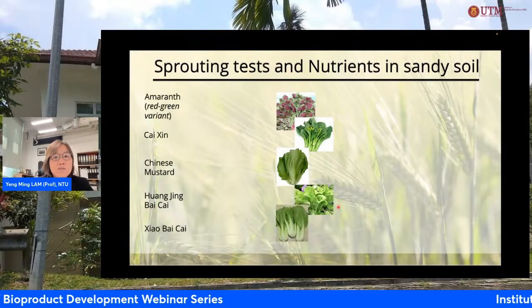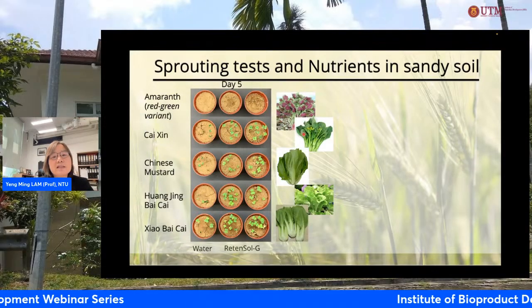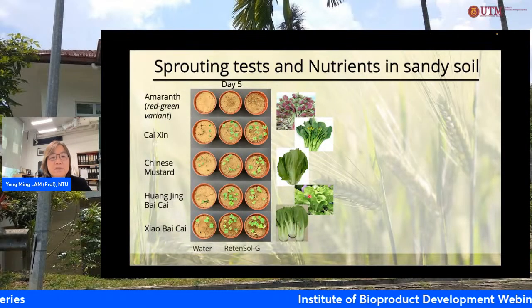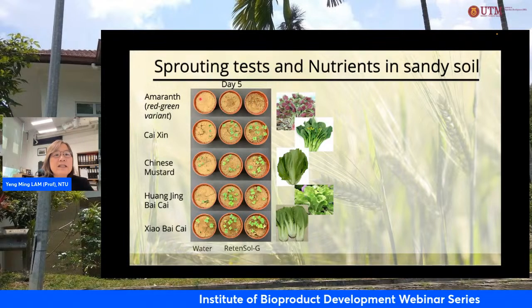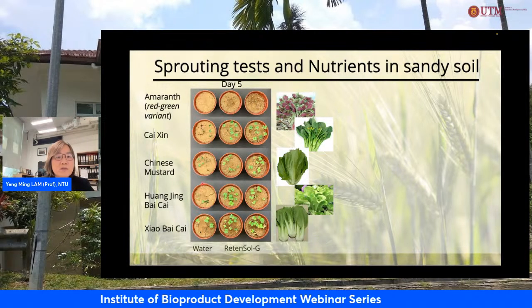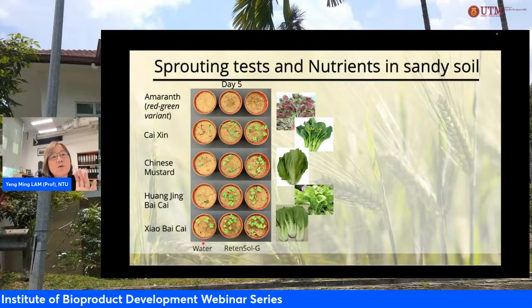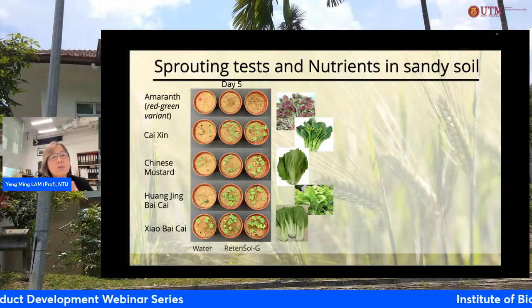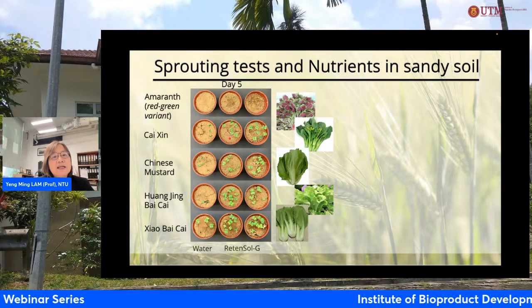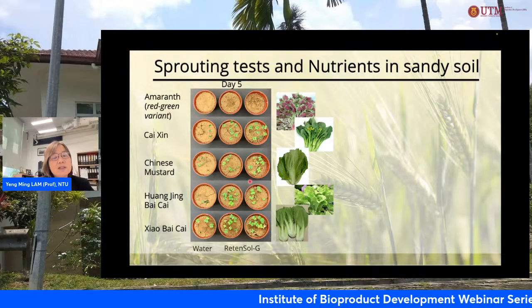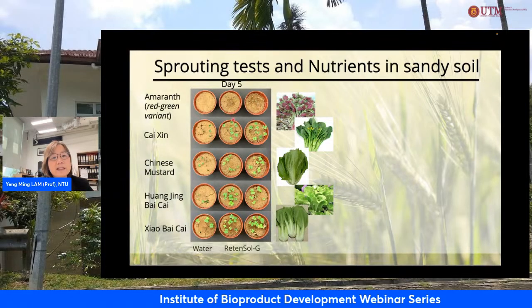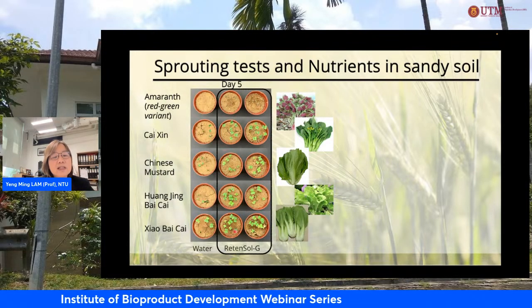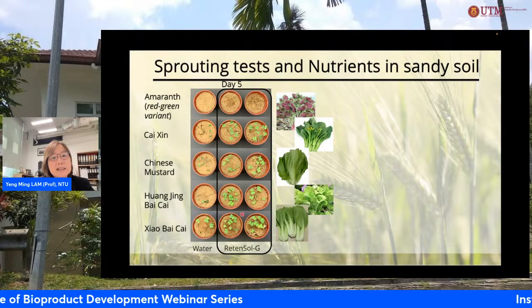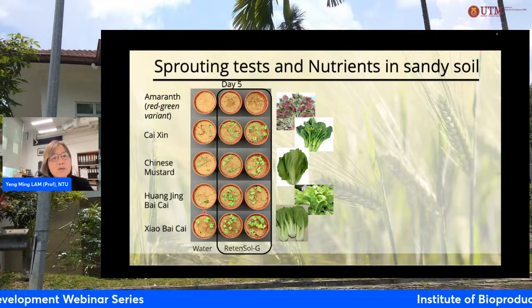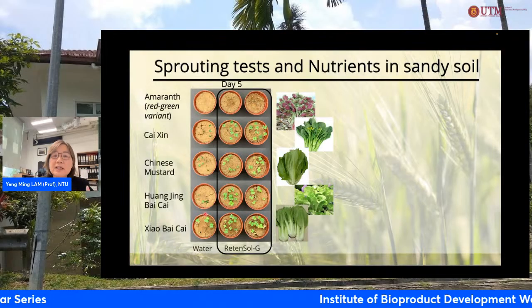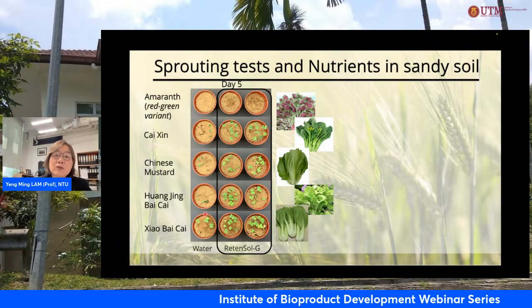So we've tested with plants. So we tried with food plants. These are actually leaves that we commonly see in Malaysia and Singapore. So in day 0, what we do is actually we water it with water, and then we leave it for 5 days without any water. So we water, and then this is actually with RetenSol-G. So this is the formulation. This is the microgel that we added in. If you look at the RetenSol-G, after 5 days, most of the seedlings stay alive, but only water will die. So it's actually essentially extend the period where you do not need water.